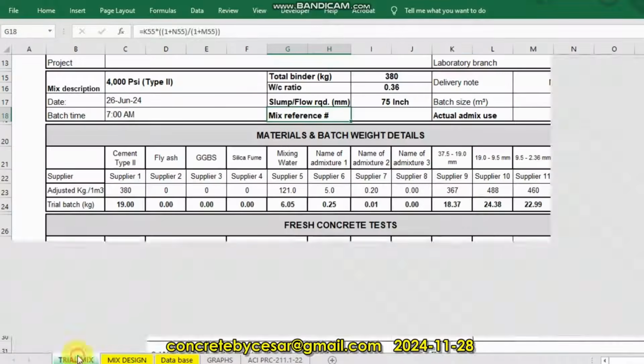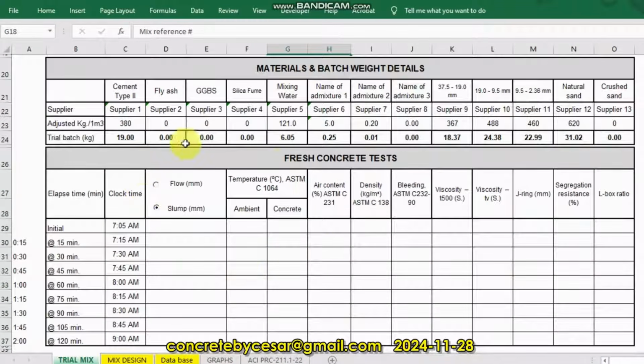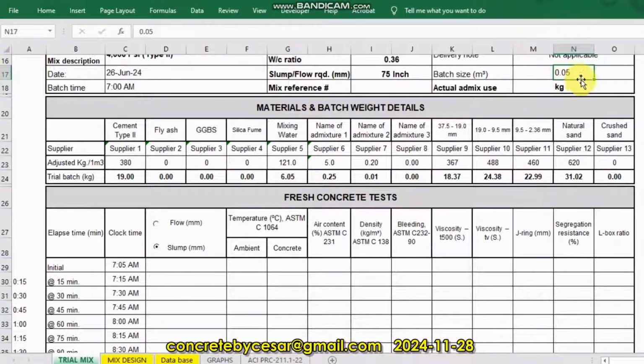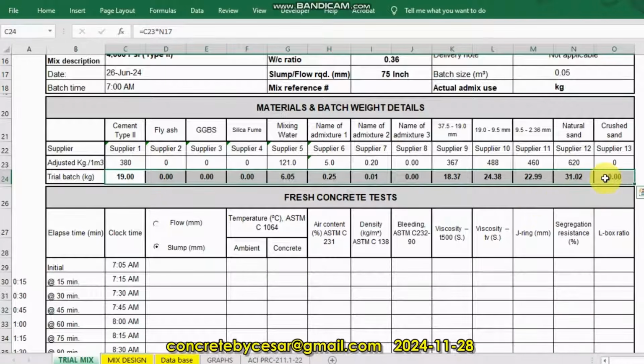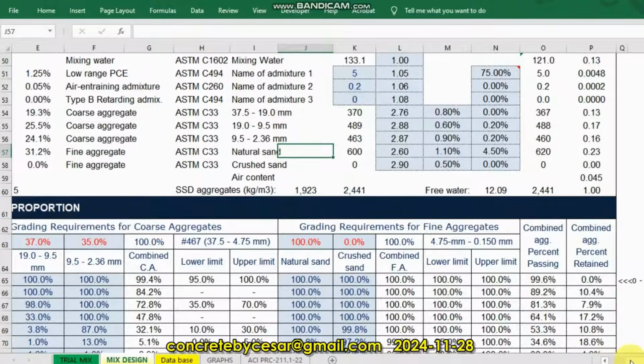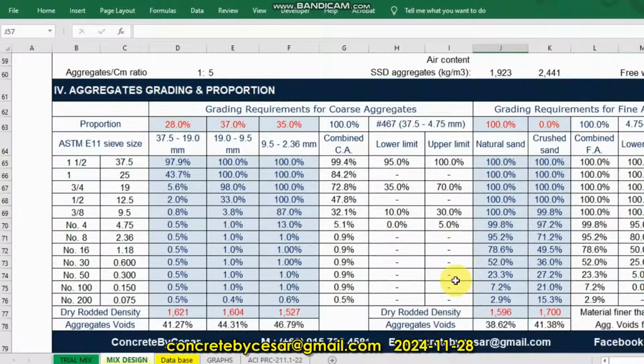So I have here also a trial mix form where you can do the lab trial, perhaps in 50 liters or 0.05 cubic meter. So this will be the value when you are trying to do a small trial batch in your lab. Next, I just want to show you again this aggregate grading proportion. So I predetermined before that this is the proportion of each aggregate size, like the 37.5 mm 28%, the 19 mm 37%, 9.5 mm 35%, which is 100% in total.